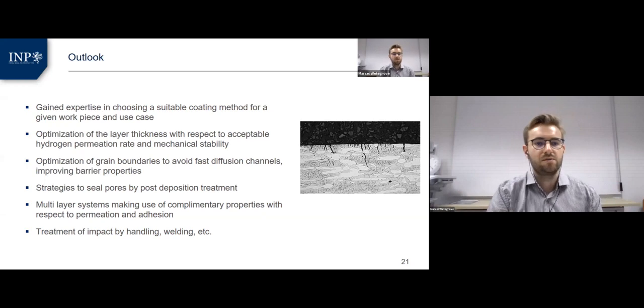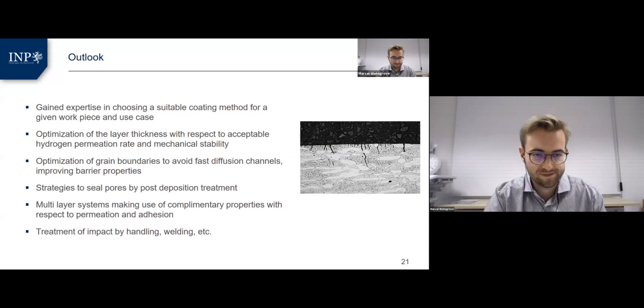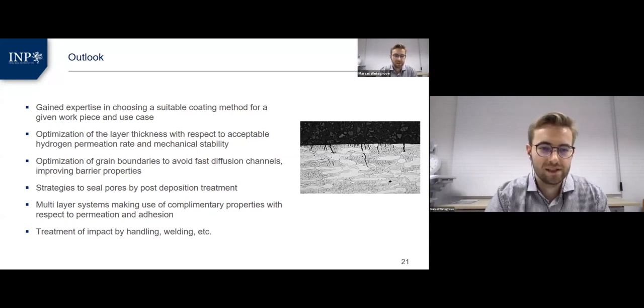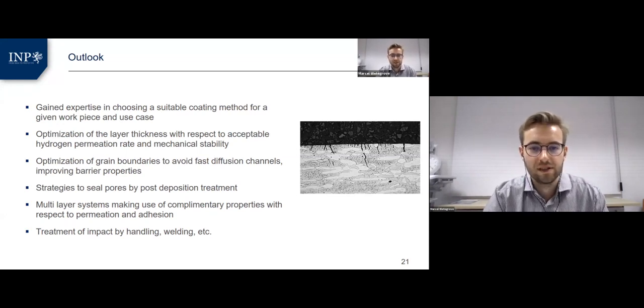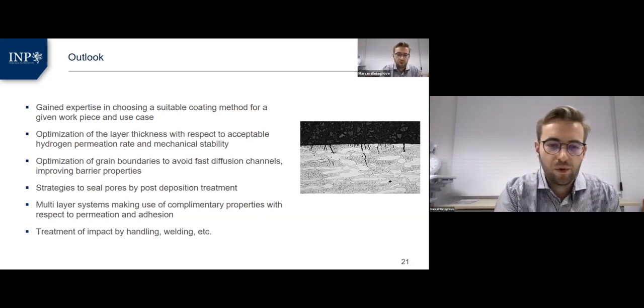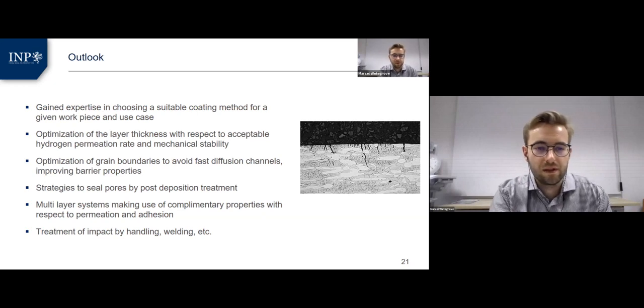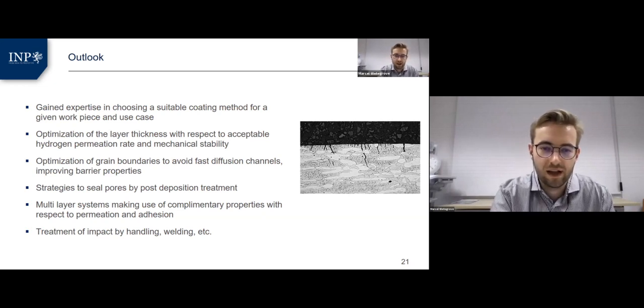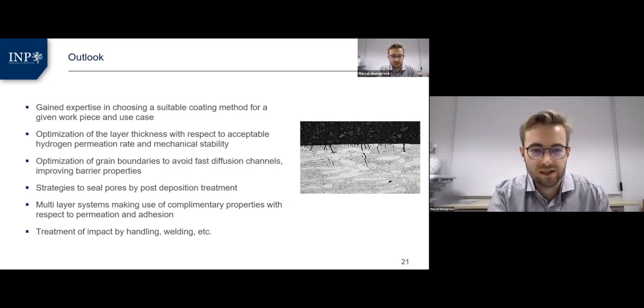We're looking at ways to seal pores, both during the deposition process and post-deposition. And also we're investigating multi-layer systems using the complementary properties of different materials with respect to permeation and adhesion. And another important part is to look into the impact that is caused by the handling and welding of workpieces, and to come up with strategies to achieve functional systems in this context.